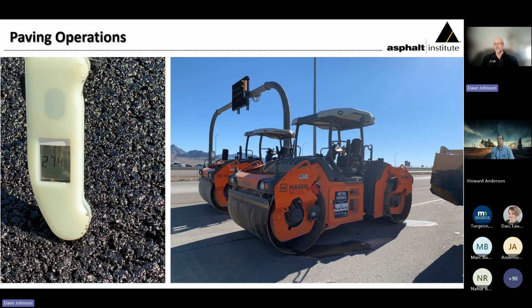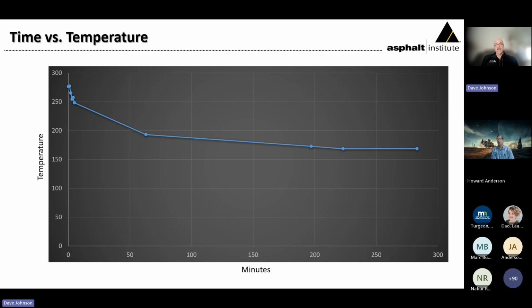The internal temperature with that 2-hour haul was about a 25-degree drop, so that placement was right at about 275 degrees. There was a temperature probe that was placed at the bottom of this, which is still active. You can still plug into it and get temperatures if you would like. But notice the long duration that it's taking this material to cool off. Thermodynamically, that truly is not a surprise. You have an incredible volume of material, and the cooling curves are very, very long because of that volume.